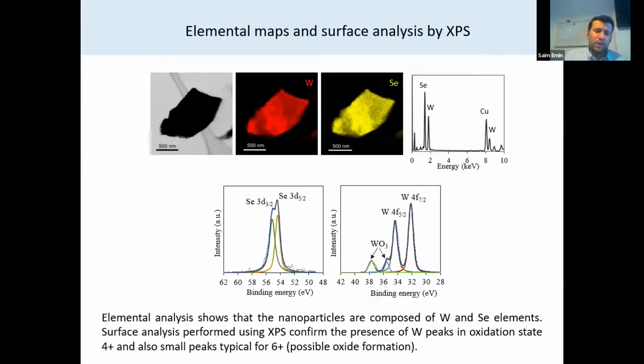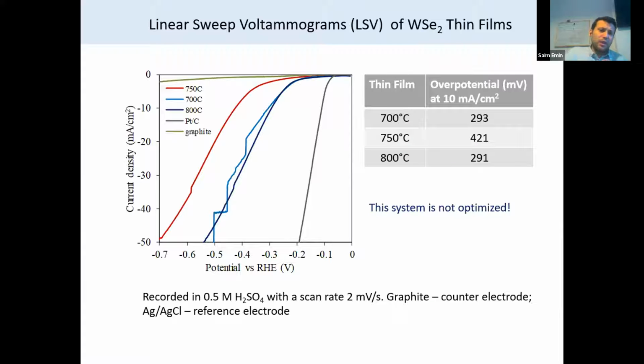With the energy dispersive spectrometer, we recorded tungsten and selenium, so we know the films are made of this material. XPS analysis also shows that on the surface we have a small layer of oxygen. Most probably it oxidized partially, but it's very little, just on the surface. And then we tested for hydrogen evolution.